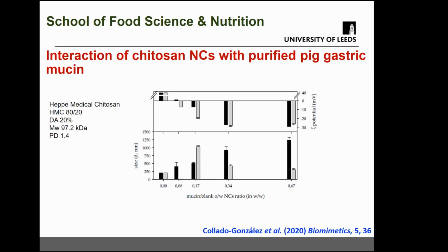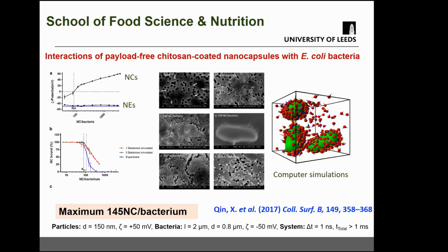The black bars are freshly prepared, whereas the gray ones are 24 hours afterwards. And we can see that for different ratios between mucin and the nanocapsules, there is a reversal of the zeta potential. So initially they are positive, and then as the amount of mucin passes a critical amount, they reverse and become negative. And then we also see that around the isoelectric point, that we could call it, the particles also grow in size. So we know that the nanocapsules interact with the glycocalyx, but also due to the presence of mucin, we could expect that.